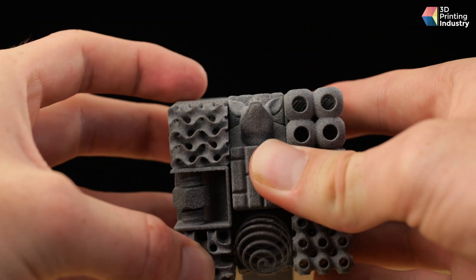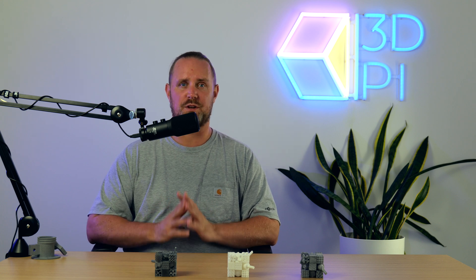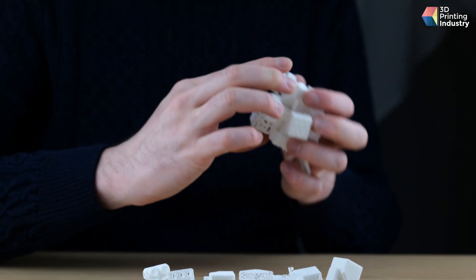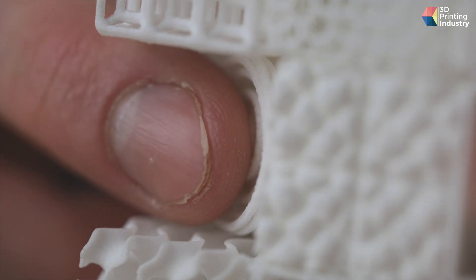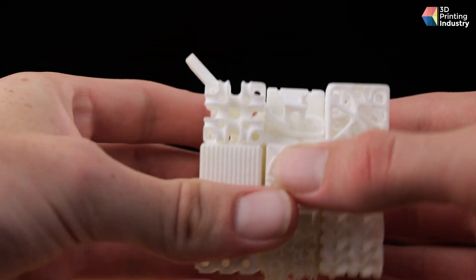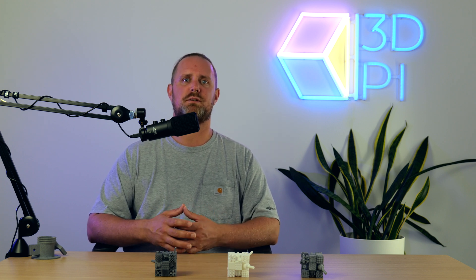While the larger cube itself did rotate — albeit with some resistance — we noticed that the HSS parts were the cleanest in terms of residual powder; we couldn't find any loose powder in the lattice cavities, so no additional post-processing was necessary. Assembling the SLS torture cube, we faced more difficulty with the six clipping faces due to excess powder in the joints. However, thanks to the smoother surface texture, the sliding corner cubes were easier to assemble. The ball and socket joint did not work, the hinge did not work, but the spring worked fine. The larger cube assembly was smooth, and we were impressed with the fluidity of the SLS assembly. Due to small volumes of residual nylon powder in the lattice structures, we had to blow out cavities and manually shake out cube elements before assembly.